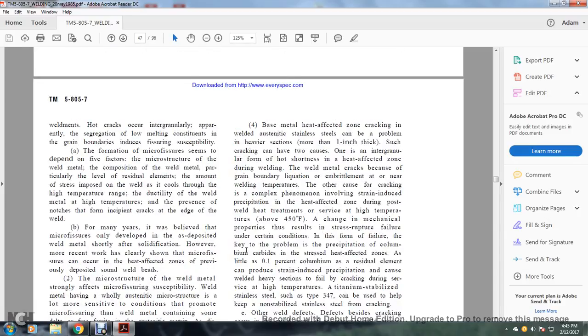4. Base metal heat affected zone. Austenitic steels have their own cracking, but there can be problems in heavier sections more than 1 inch in thickness. Such cracking can have two causes. One is the intergranular form of hot shortness of the heat affected zone during welding. The weld metal cracks because of grain boundary liquation and embrittlement at near-welding temperatures. The other cause is a complex phenomenon involving strain-induced embrittlement of the heat affected zone during post-weld heat treatments.